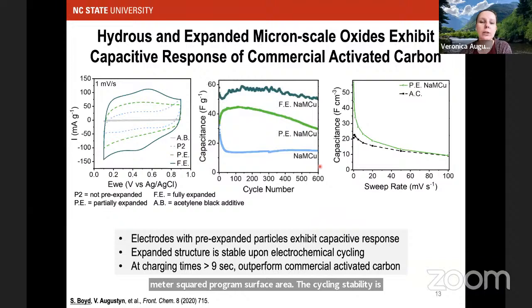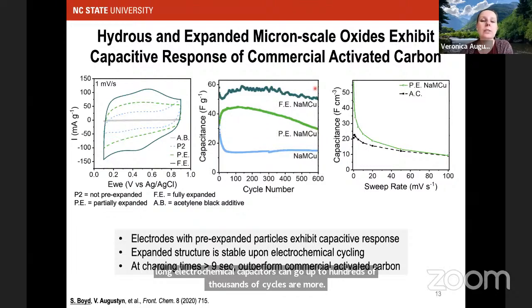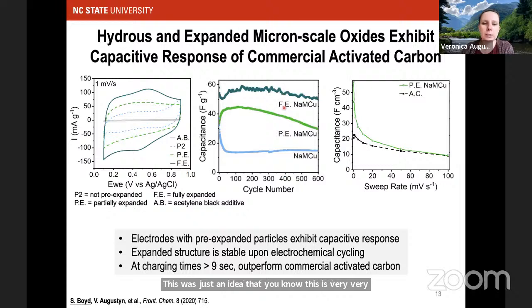We didn't cycle for long. Electrochemical capacitors can go up to hundreds of thousands of cycles or more. This was just an idea that this is very, very stable cycling that you can obtain. The prefixes here, the FE and the PE, just stand for whether we could obtain a fully expanded or a partially expanded material, which has to do with how well we can electrically connect all the particles in that pouch to drive sodium out of them.